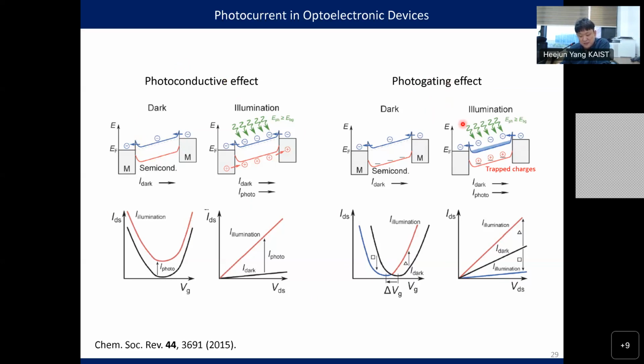Okay. And another effect is called the photogating effect. If we illuminate some light, we have charge traps. And then these trapped charges are gating the channel again. So the result is, this is called the transfer curve. So for an n-type semiconductor, we have this transfer curve. And then if we illuminate light, this transfer curve can be shifted in terms of gate bias. In this case, sometimes we have lower current under light illumination, and sometimes we have higher current under the light illumination. And in most cases, they are mixed.